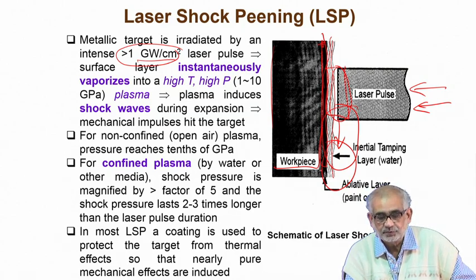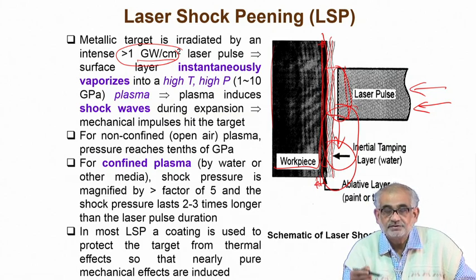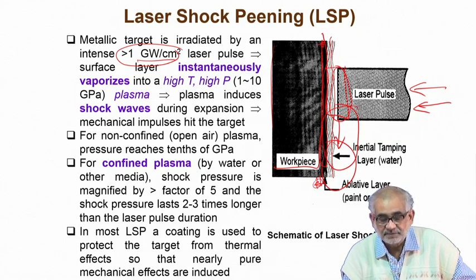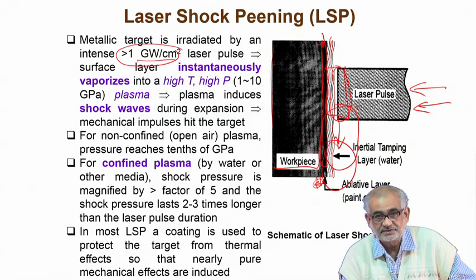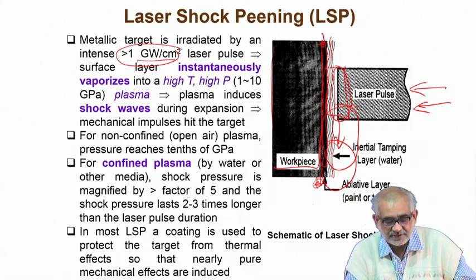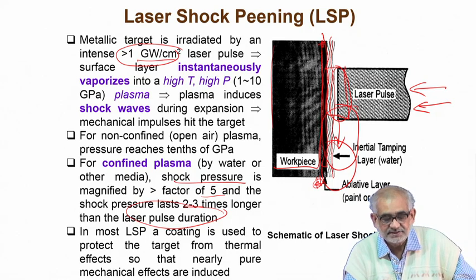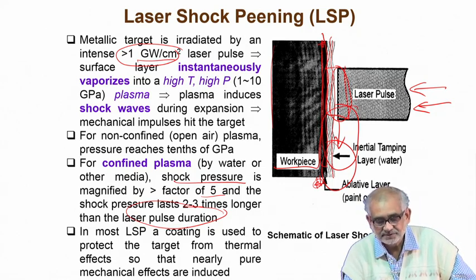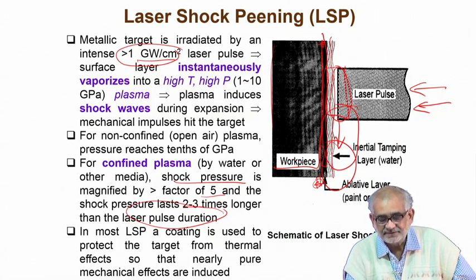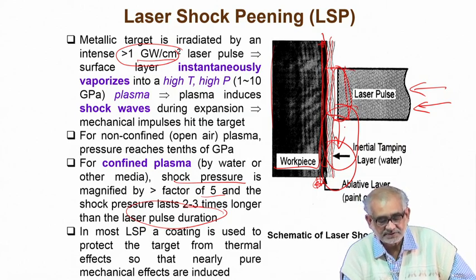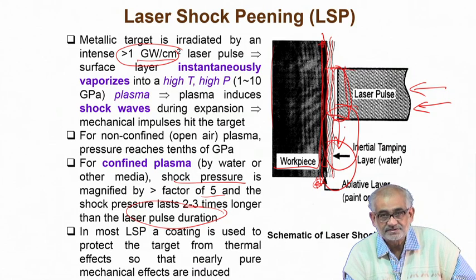The amount of deformation that propagates is smaller, but when you irradiate the smaller zone with very high power, the effective stress is much higher than in ultrasonic peening or shot peening. As a result, you can create a shock pressure which is much higher — by a factor of 5 — and can last 2 to 3 times longer than the laser pulse duration. In other words, if the pulse duration is a millisecond or microsecond, the effect lasts for a longer period of time, and the area affected is wider than the beam diameter of 1 or 2 millimeters.